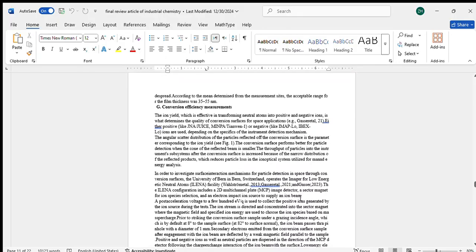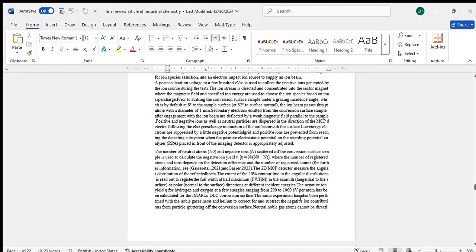G. Conversion efficiency measurements. The number of the neutral atoms and the negative ions scattered off the conversion surface sample is used to calculate the negative ion yield, where the number of registered atoms and ions depends on the detection efficiency and the number of registered counter informations. And from this article you can see the explanation of these designs. The 2D MCP detector measures the angular distribution of the reflected beam.